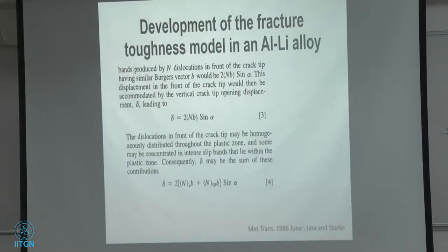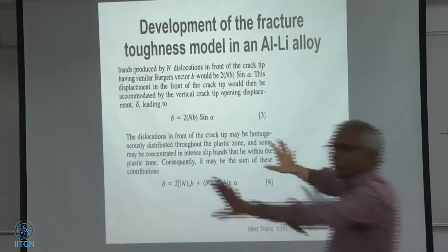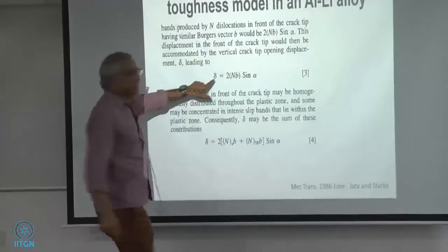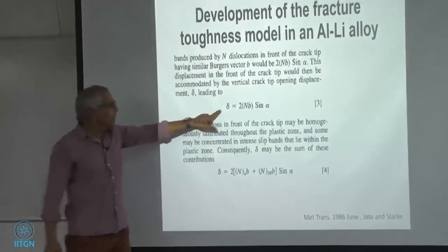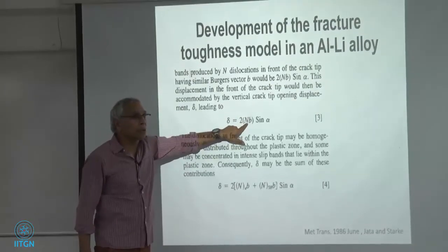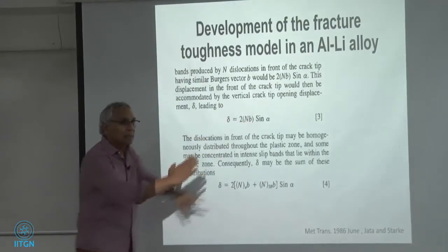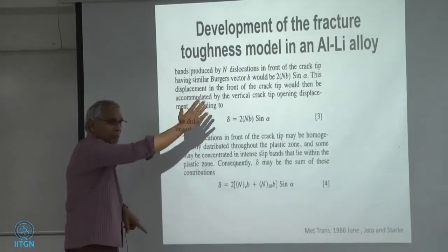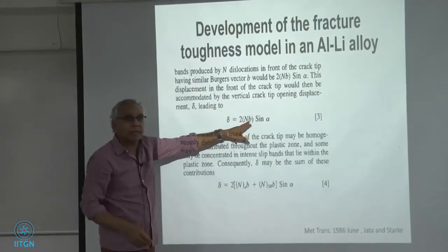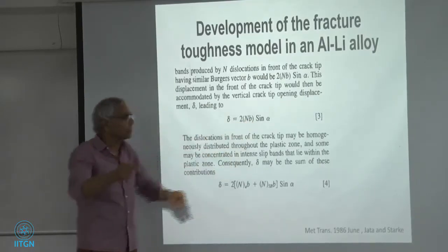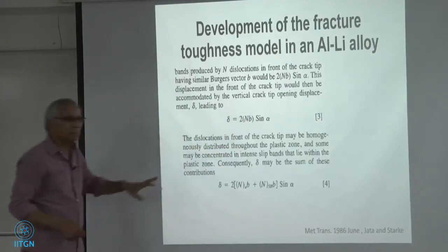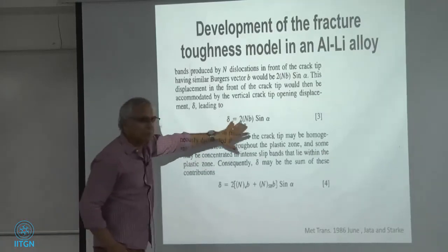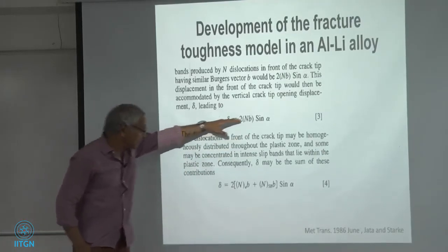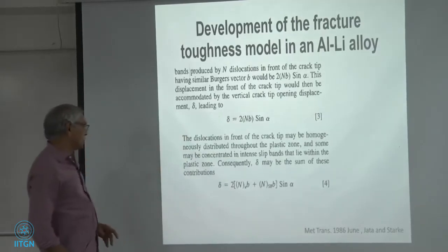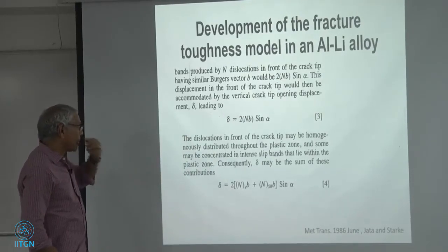So here is the model. I just kind of put more steps in here. So this is the crack. Don't pick my mistakes here. So here is the crack opening displacement, okay? In front of the crack opening displacement, number of dislocations times Burger's vector. Alpha is the inclination of the slip band. On that slip band, you have n dislocations times Burger's vector for each, okay? This twice comes because you can put 3, no, you can 2, okay, that's fine. And then these slip bands, we divided them up into 2 parts, okay?